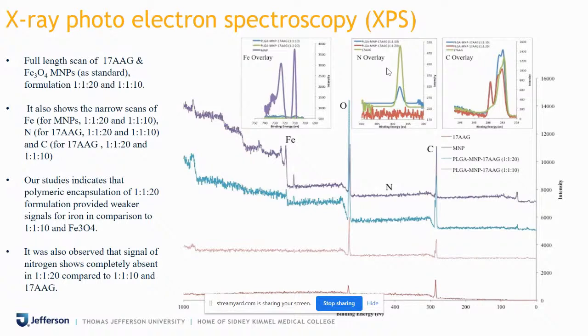The problem with Fe with the XPS technique is that it is a surface phenomenon. The characteristic X-rays come out from within the material, but XPS is a surface measurement. So it's measuring the signals from the molecules which are sticking on the surface of the molecule. Because we cannot control the self-assembly of the molecule, if the molecule is sticking outside, it's very easy to get a good signal. But Fe is within the shell, so it's very difficult to get a signal through the polymer. But we had a small bump over here, and along with the TEM measurement and EDS, we were able to confirm that Fe is there.